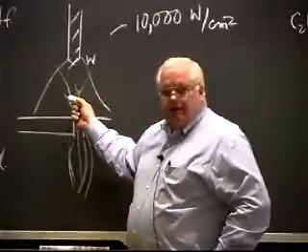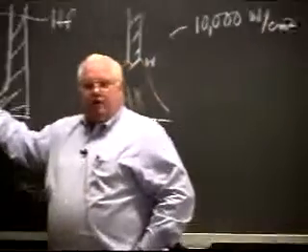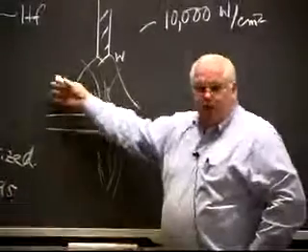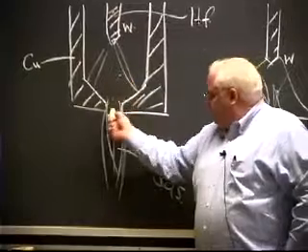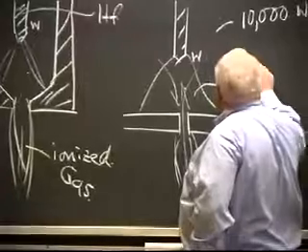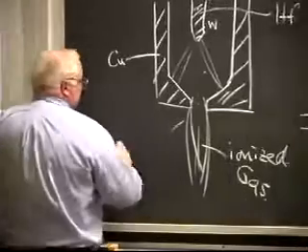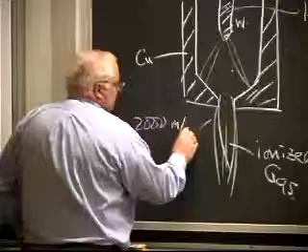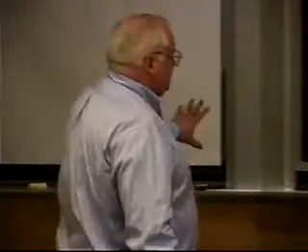So this is a gas tungsten arc burning at constant pressure. This is a gas tungsten arc burning at constant volume. And this is going to have a higher volume. This one is just free expansion at 1 atmosphere pressure. This one is no expansion. It's constrained and it's expanding out this one little hole, which gives it a higher velocity. The velocity here is going to be on the order of 100 to 500 meters per second. The velocity here can be supersonic, but let's just put in a number, 2,000 meters per second. It depends on the size of the hole and everything else. But it can be a substantially higher velocity.